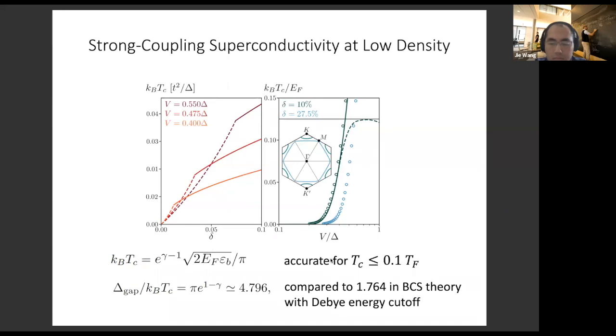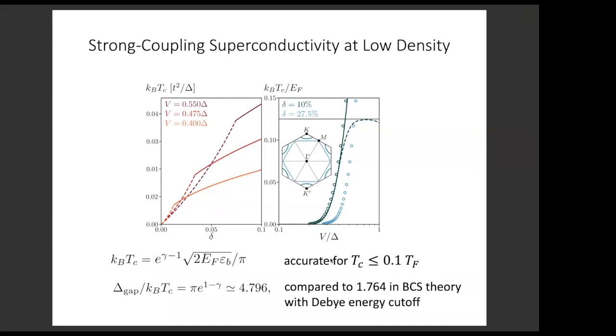And also, I want to emphasize that even though the doped electrons are in the BCS limit, the ratio of the gap to T_C is 4.79, much larger than the BCS value. And the reason is the following. In the BCS theory applied to conventional metals, the pairing interaction is limited within the Debye frequency range, and the Debye frequency is much smaller than the Fermi energy. While here, in our case, as well as in actual cold atom systems, the pairing interaction is non-retarded. It spreads over the entire narrow bands, and the bandwidth is larger than the Fermi energy. So in that case, T_C receives contribution from all states in the band, not just from a narrow window around the Fermi energy. So because of that, delta over T_C is much larger.